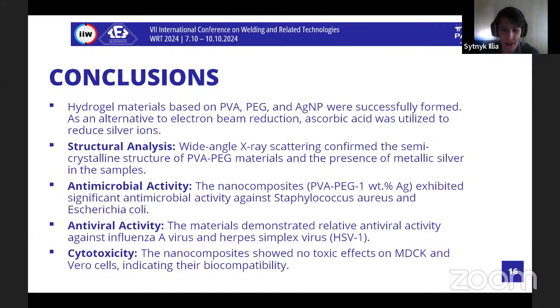Using the method of wide-angle X-ray scattering, it was established that hydrogel materials based on PVA-PEG form a semi-crystalline structure, and the presence of metallic silver in the studied samples was confirmed. It was established that polymeric hydrogel materials with silver exhibit antimicrobial activity against Staphylococcus aureus and Escherichia coli and relative antiviral activity against influenza A virus and herpes simplex virus. It was established that the studied polymer hydrogel materials with silver nanoparticles do not show a toxic effect on MDCK and Vero cells.